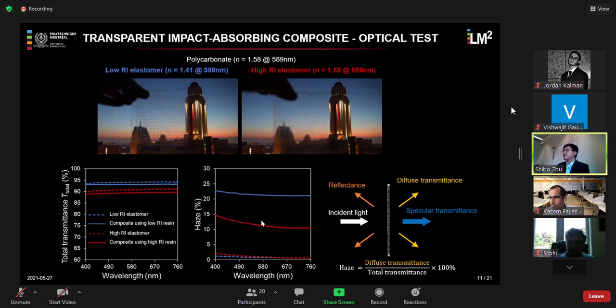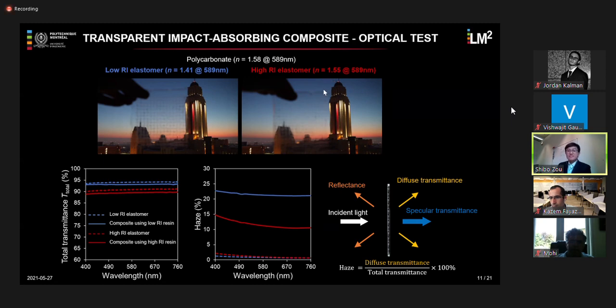As you can see here, in the high RI elastomer-based composite, in which the refractive index of the matrix material is much closer to the fiber itself, we have almost half of the haze of the low RI elastomer composite, in which the difference between the matrix refractive index and the fiber's refractive index is much higher.